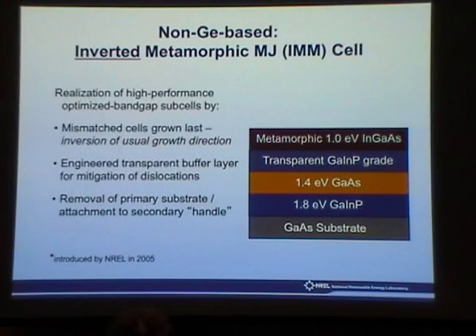So what we did at NREL is try to move beyond the germanium-based cell, and we developed what's called the inverted metamorphic multijunction cell. It's a bit of a mouthful, so we abbreviate it to the IMM. It's probably the best platform for achieving the optimum band gaps, and it has the following advantages. You grow the device upside down. You grow the top cells first, followed by the bottom cells. And if the top cells are lattice matched, and they are, that means the most energy-productive element of your cell is being grown with the highest material quality. Whereas in the germanium-based cells, the dislocations are formed first, and then you grow these really high-quality top cells, here you do the opposite. So you have really high-quality material in the most important of the subcells, and you may sacrifice some material quality in this cell, but it's not as important.